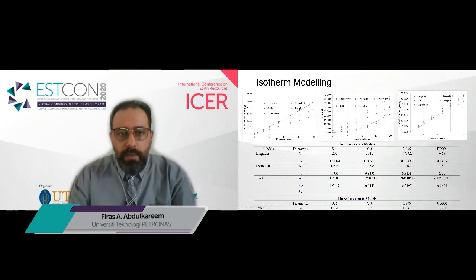And on the isotherm modeling, we can see that Langmuir, Freundlich, Temkin, and Toth show more or less good agreement with the experimental data. However, Langmuir shows the highest agreement compared to the others. As we can see here, Langmuir is more or less fitting the experimental data exactly, supporting the monolayer coverage of the gas molecules on the surface of the shale sample. We also have Temkin showing good agreement with the experimental data here and here.